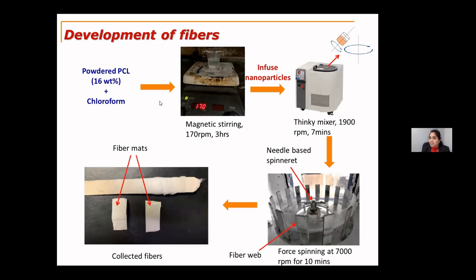And then we mix them through magnetic stirring. I chose 170 RPM, and this is a magnet here, which is a white thing. So magnetic stirring was done for 3 hours at 170 RPM. That way, the polycaprolactone powder will be dissolved in the chloroform completely. And after that, we infuse the nanoparticles into this solution.